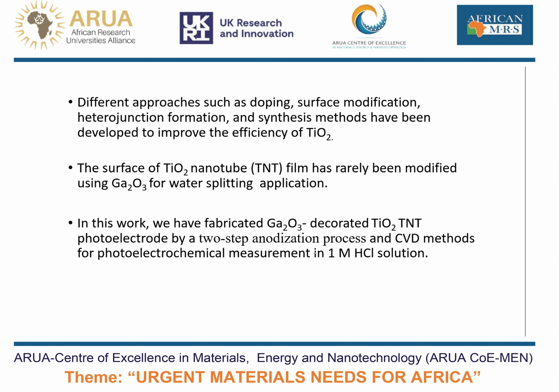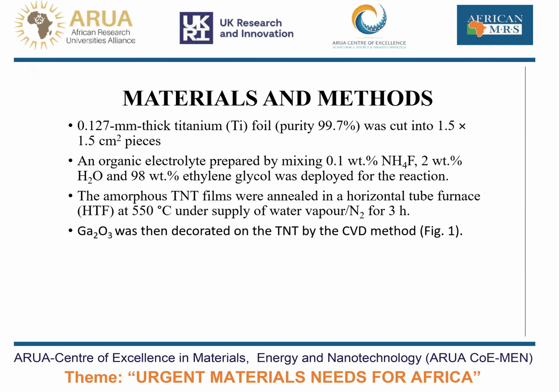towards photoelectrochemical measurement in 1 molar hydrogen chloride solution. Materials and methods. We made use of titanium foil of the stated thickness and purity of 99.7%. The titanium foil was cut into pieces of size 1.5 by 1.5 cm as the substrate for the anodization in order to produce the titanium nanotubes.